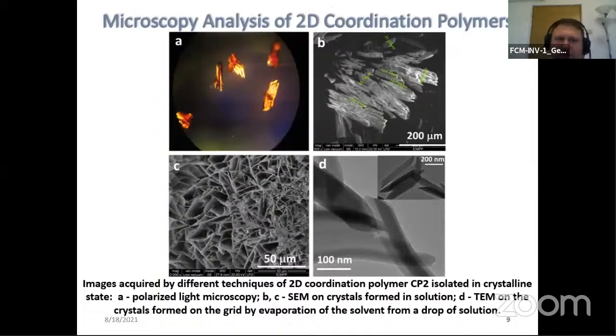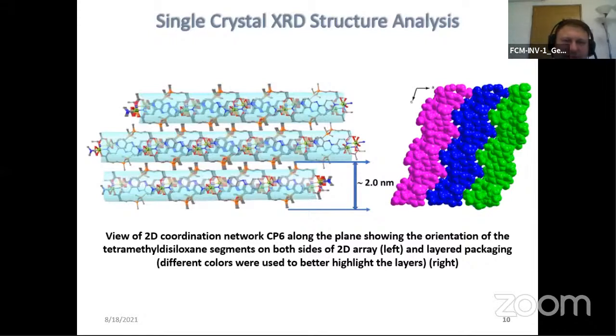These coordination polymers can be isolated as single crystals and were analyzed by polarized light microscopy, scanning electron microscopy, and transmission electron microscopy, as can be seen in these images. Also, by X-ray diffraction, we can see the orientation of the tetramethyl disiloxane segments on both sides of the two-dimensional array in the left side image, and the packaging of the layers on the right side image. The two-dimensional layers interact by van der Waals forces.